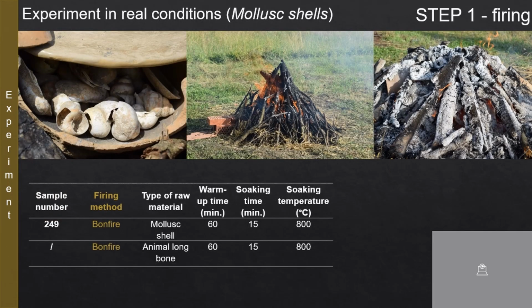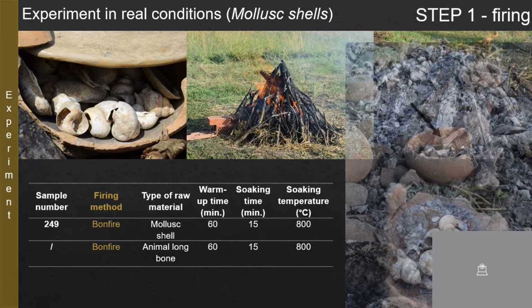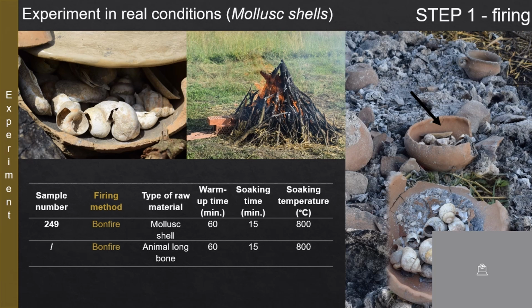The initial experiment was conducted in an open fire with short soaking time. Mollusk shells were placed inside a ceramic vessel, covered and placed in the center of the bonfire. After an hour, the firing process ended and the shells were removed while still hot.